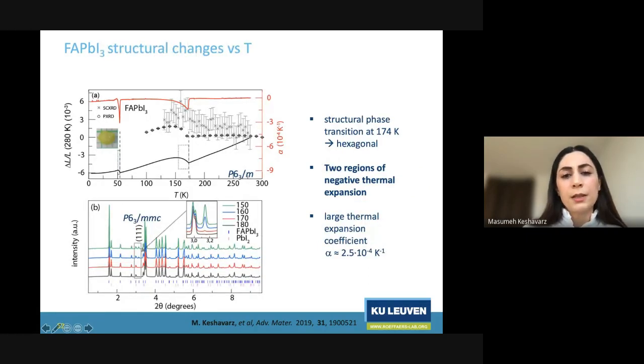So we observed the transition from a high order hexagonal to a lower symmetry hexagonal for the formamidinium lead iodide, but below 50K we also see a structural change, which we couldn't access through XRD measurements, so we don't know what the phase is, or whether it is a distortion, or even ferroelectric domains or whatever. And we also see two large negative thermal expansion regions in this material, which has never been observed before, with a very large negative thermal expansion coefficient compared to known materials. This can also open more applications for perovskites.